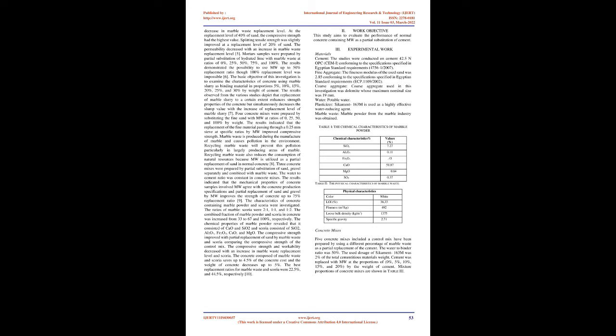The acid attack resistance, carbonation resistance, and water absorption were determined to evaluate durability properties. The results showed that marble waste and coconut fiber decreased the workability of fresh concrete. The mechanical properties of hardened concrete were enhanced by MW and coconut fiber up to 20% and 2% replacement ratio of cement weight, respectively. There is a significant improvement in durability properties with partial replacement of cement by marble waste and coconut fiber too.